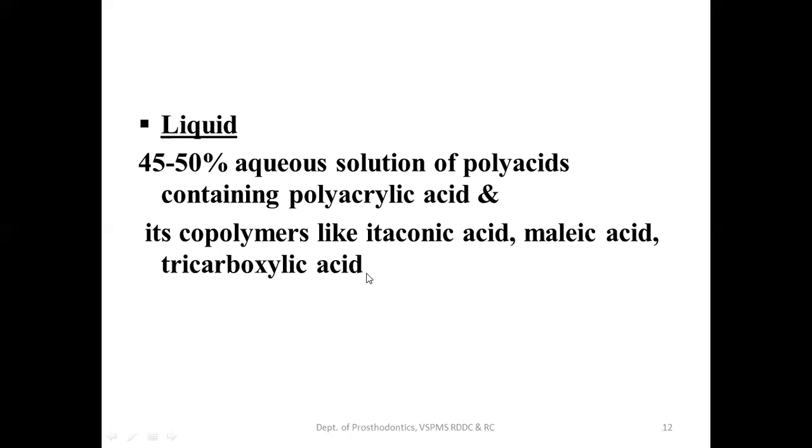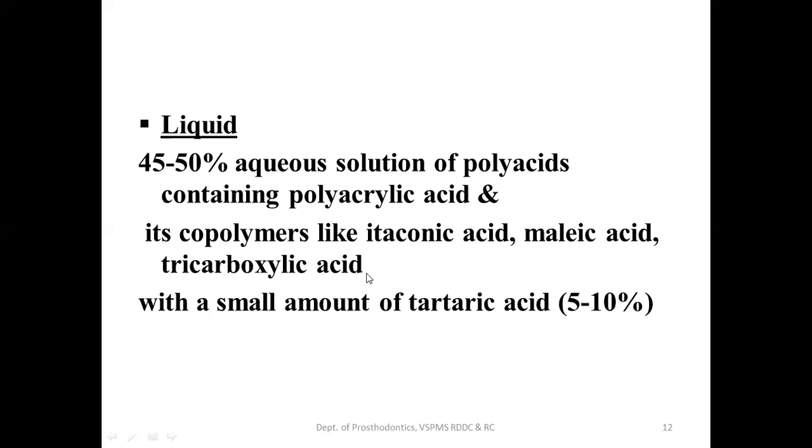hydrogen bonding. The next important liquid content is tartaric acid, which is around 5 to 10%, and this is important to increase the working time and to decrease the setting time, and it also prevents the thickening of the liquid during storage. In one of the MDS examinations, the role of tartaric acid was asked in an MCQ, so please remember this. Now coming to the setting reaction, which is very, very important.